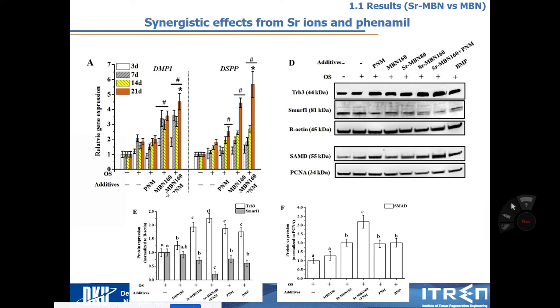And then after loading this phenamil in my strontium bioglass, I wanted to compare their bioactivity. So this is the phenamil only, which is loaded in nanoparticle. And then in this nanoparticle, the strontium plus phenamil. As you can see, DMP1 and DSPP gene expression is highly increased compared to strontium MBN and phenamil in strontium plus phenamil. And then to reveal the underlying mechanism, I checked the protein level by Western blot. I saw the strontium plus phenamil group had more TRB3 increased, SMURF1 decreased, and then SMAD increased. And this is very similar to the amount of the BMP. This is positive control. So without BMP, I can accelerate this human odontoblast differentiation in strontium doped bioglass with phenamil. And then this is a semi-quantification of this Western blot band.